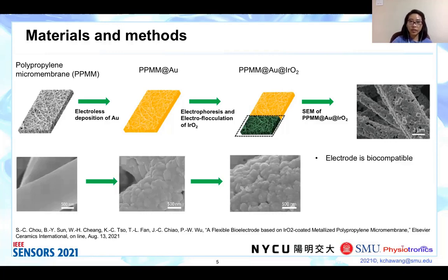The electrode is biocompatible and has chemical inertness. Among other metal oxides, iridium oxide is known for its biocompatibility, super-Nernstian sensitivity, and wide pH sensing range. It can be used as multifunctional bioelectrode for wearable and implantable devices. The fabrication process also did not require high temperature. Gold was deposited at 30 degrees Celsius and iridium oxide at room temperature.